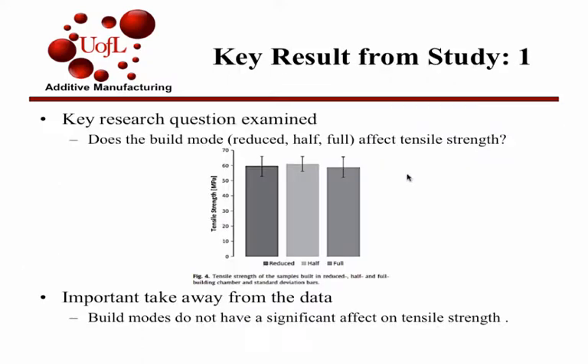The very first thing that was tested was: does the build mode affect tensile strength? You have a full chamber size, which is 700 by 380 millimeters. All sides of the powder bed are in contact with heaters, and the very top of the powder bed is exposed to the atmosphere. The half-size chamber is 350 by 380 millimeters, and only three sides are directly heated by the heaters within the powder bed, and the other side is exposed to the atmosphere of the machine itself. The reduced build mode is 350 by 250 millimeters, and two sides are heated within the powder bed itself, and the other two sides are exposed.